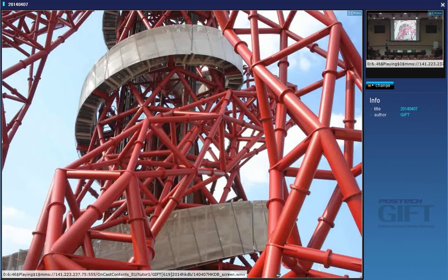You can see these are pictures that I took. Basically, almost all structural steel will consist of mixtures of ferrite and pearlite. The strength levels might be as low as 250 megapascals and going up to something like 500 megapascals, but you don't go much beyond that, because welding becomes an issue. So the vast majority of structural steels are not really that strong when you compare with what you're trying to do with TRIP steels and automotive steels and so on. The strength levels are quite small. 400 megapascals is quite typical for structural steels. I don't actually know exactly what kind of steel this is, but whenever there's a large scale application, you'll be looking at materials with strengths of the order of 400 megapascals.